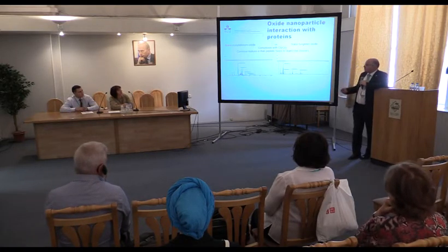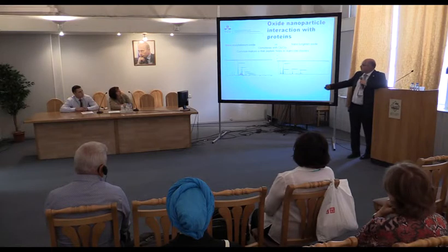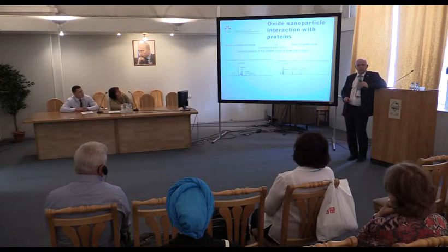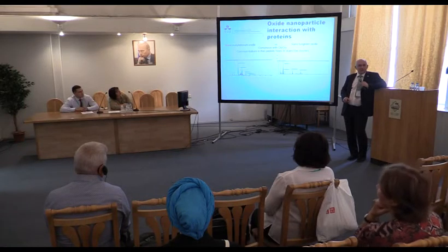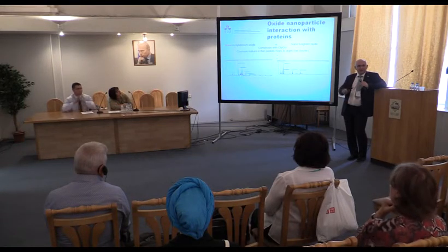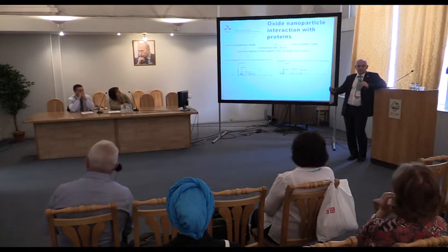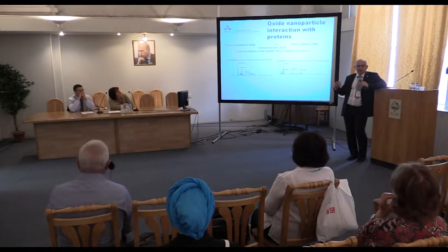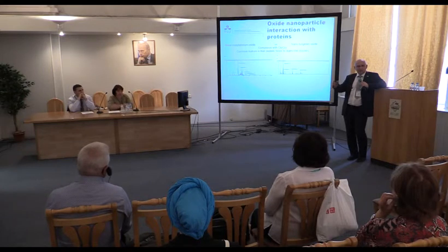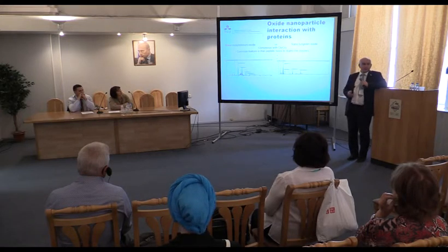But what we were able to see was that both for molybdate and for tungstate, in solution, we saw a very complex equilibrium. So there was very little of intact particles, let's say, in the presence of this simple peptide in solution. Because we followed this process also with NMR, we saw that they were dissolving as particles and peptide, but with time they were transforming into very complex mixtures. And this is the equilibrium mixture after 24 hours.